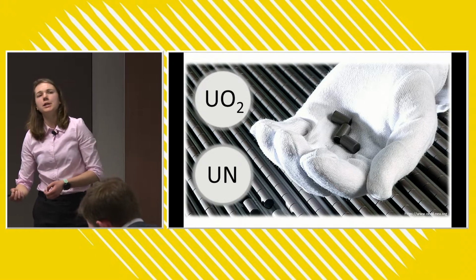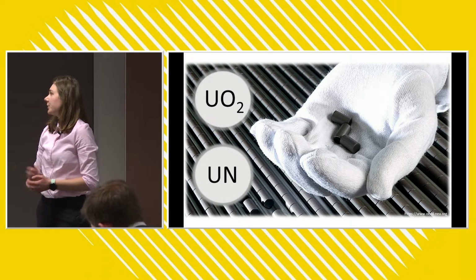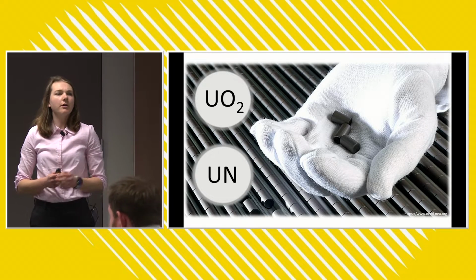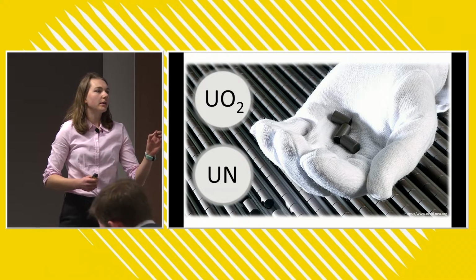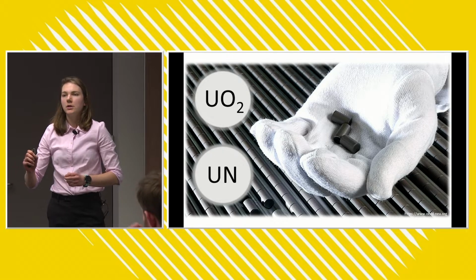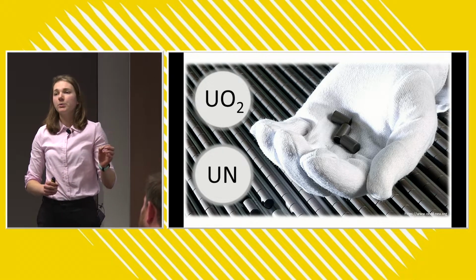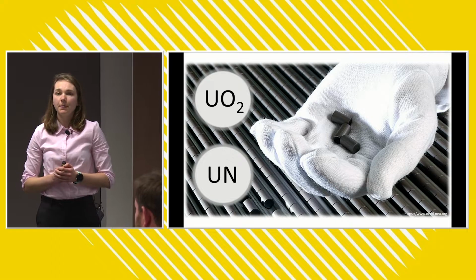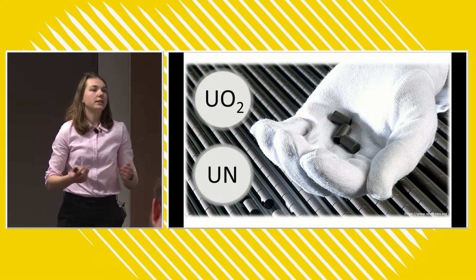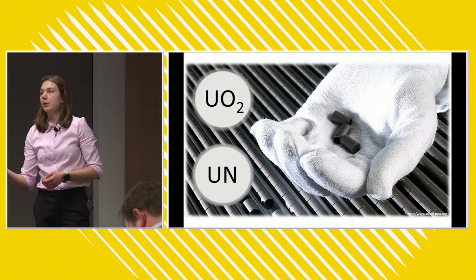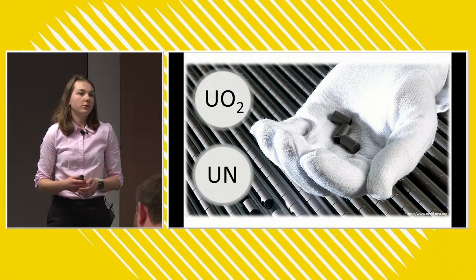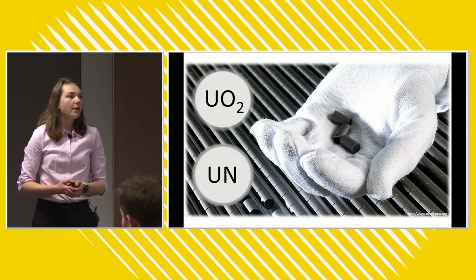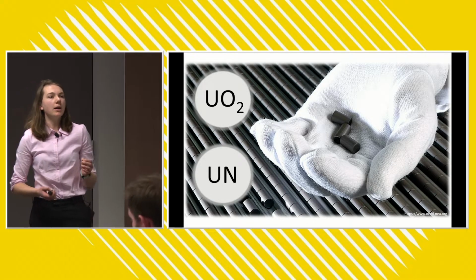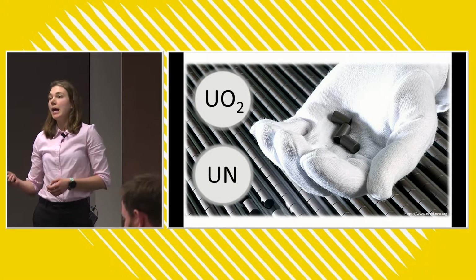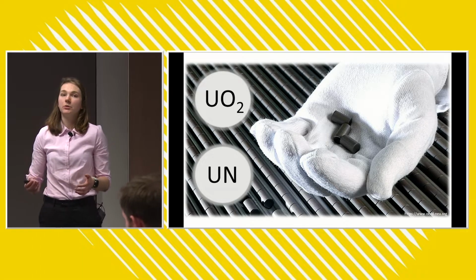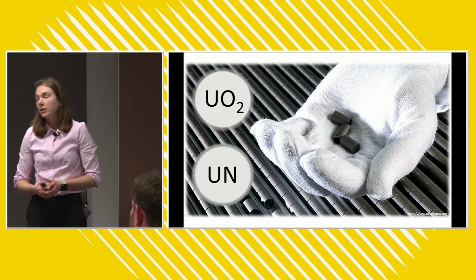So if we think for a second about the chemical formulas of those two fuel materials, we've got uranium dioxide, UO2, which has 1 uranium for every 2 oxygens. Whereas with uranium nitride, UN, we have a 1-to-1 ratio of uranium to nitrogen. So that means we've got a higher density of uranium, the component that's responsible for the heat production, in uranium nitride fuel. So that means if we want to produce the same amount of electricity, we can use less nuclear fuel, which leads to the production of less nuclear waste.